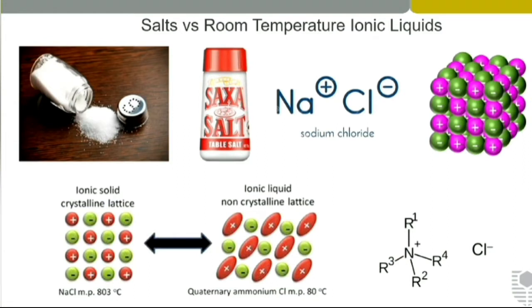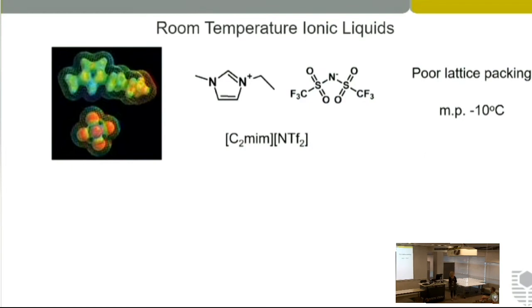But now if you change the chemistry of the ions, and particularly if you make one of the ions, in this case the cation, asymmetric, as in a quaternary ammonium chloride, you can see that we've reduced the melting point from 800 degrees down to about 80 degrees. The reason is that we now have a disrupted lattice structure. We can push this even further and make both the cation and the anion larger and more asymmetric, disrupting the lattice even more, and that's where we end up with room temperature ionic liquids.